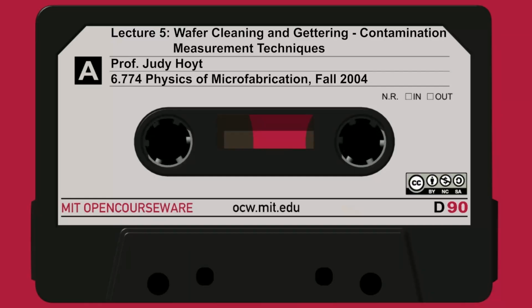So let's go on to slide 9. So this TXRF, what are some of the good things about it? Well, I just showed you it's a survey technique. You get a broad idea of what different elements are on the wafer, and it can be automated. It's reasonably quantitative. We can integrate those peaks and compare them to standards. It doesn't destroy the wafer. You notice the X-ray just comes in, interacts, and goes out. It's not like I have to sputter off or break the wafer. You can do it on an entire wafer. They have machines for 12-inch wafers you can put in there, and they'll tell you what impurities are on that wafer surface. So that's really nice.